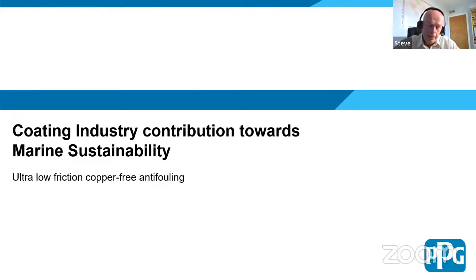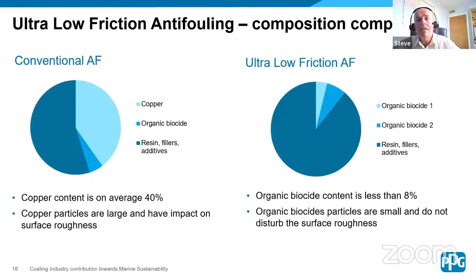And that has an interesting element in its own right, in that a conventional antifouling has a significant portion of its formulation, represented as a pie chart here, as cuprous oxide, normally supported with an organic co-biocide to give it enhanced protection against fouling organisms such as slimes and bacterial slimes. But there's a lot of it. Whereas by targeting with specific organic biocides, we reduce the biocide content dramatically. So there's a lot less biocide actually being released into the environment and yet still providing outstanding performance.